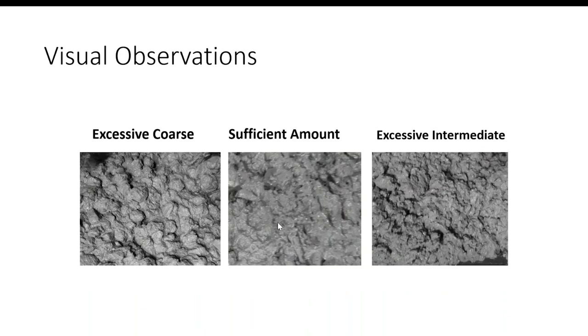So same thing about finishing. If I had just right in the middle, boom. Too much intermediate. Oh, look at that. It's all bony looking. Too much coarse. Oh, it looks bony again. Looks like it's going to be hard to finish. That rock is like coming out of the mix. The tarantula curve helps you get it just right.